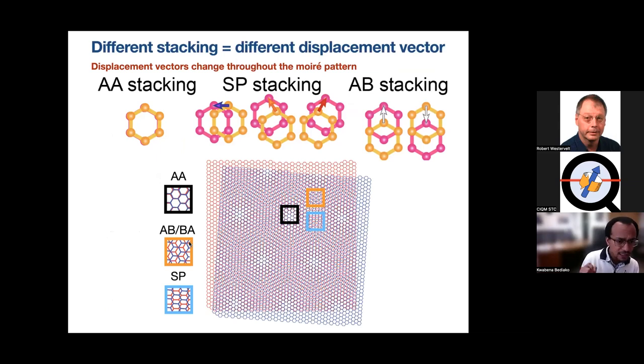Okay, now to understand exactly what happens and how this interferometry works, we need to understand that the modulation in crystallographic registry that we see can be represented in terms of a displacement vector, which is simply the vector connecting one carbon atom in one layer to its counterpart atom in the other layer. So AA stacking, for instance, has a displacement vector of magnitude zero, and then saddle point, these intermediate stackings, or AB and BA, those have finite displacement vector magnitudes and specific directions.